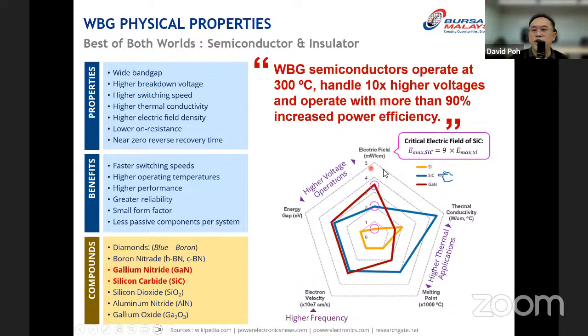Now, this breakdown voltage is related to the critical electric field, which I talked about just now. So for SiC particularly, the critical field is 9 times stronger than the normal silicon. What that means is the silicon carbide material can withstand a much, much higher voltage compared to the silicon before the material breaks down.